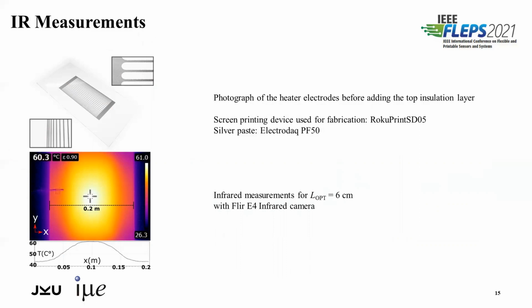The screen is flooded with paste and the heater structures are printed through the screen with a semi-automatic screen printing machine. We use Electrodag PF50 as silver paste to print these heaters. Finally, the lower figure shows an infrared measurement using a FLIR E4 infrared camera. The numerical temperature values have been cross-checked using a PT100 temperature probe visible on the left edge of the substrate. We can see that the simulated temperature plateau of 60 degrees Celsius has been hit almost exactly.